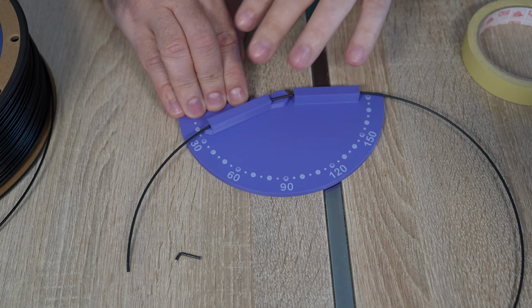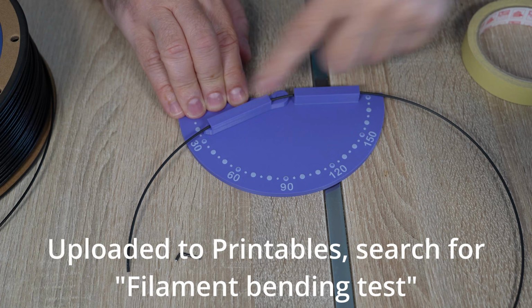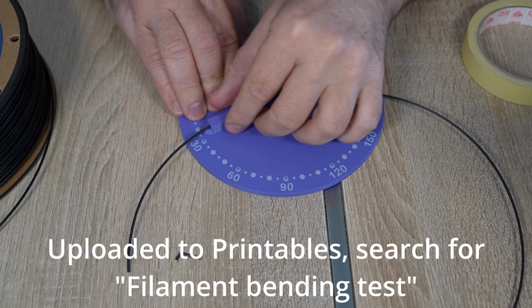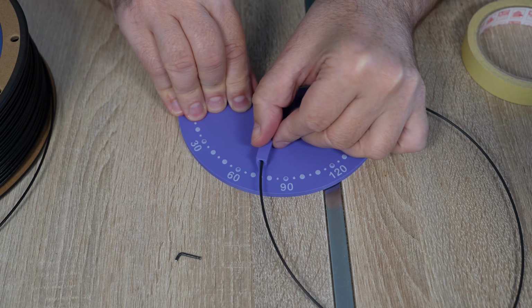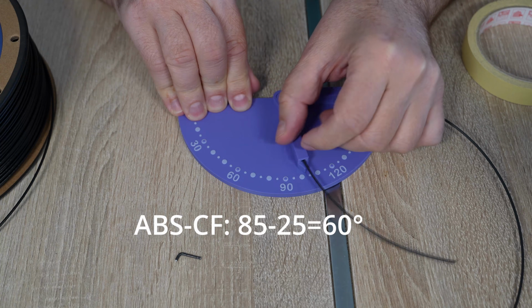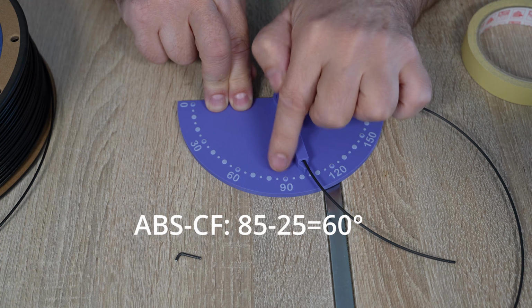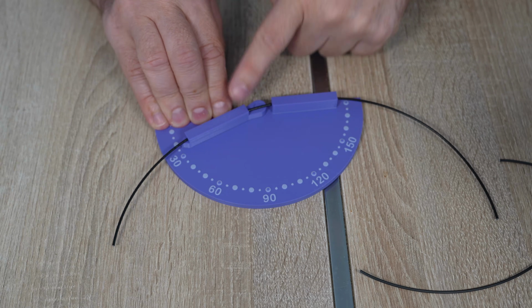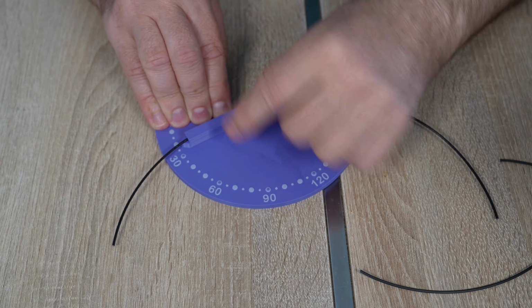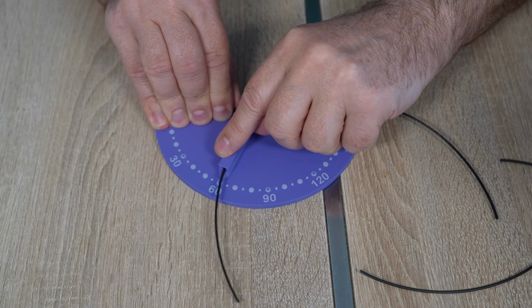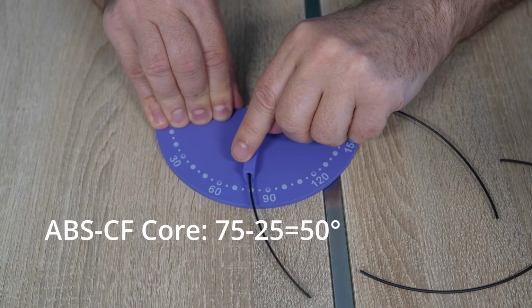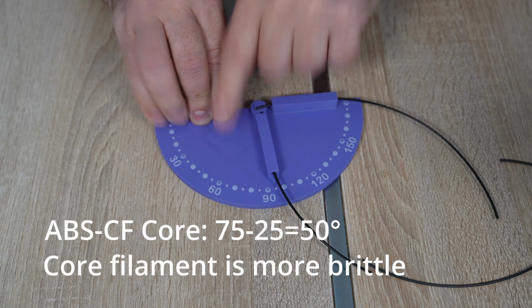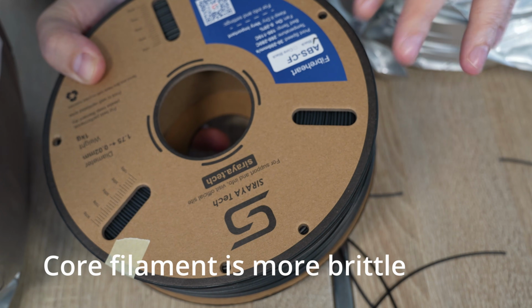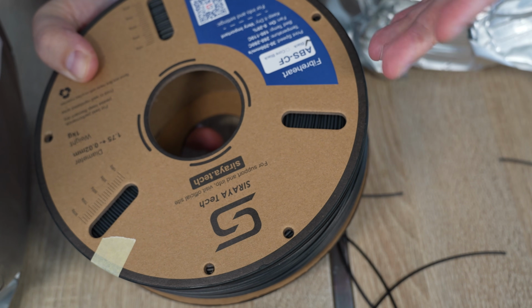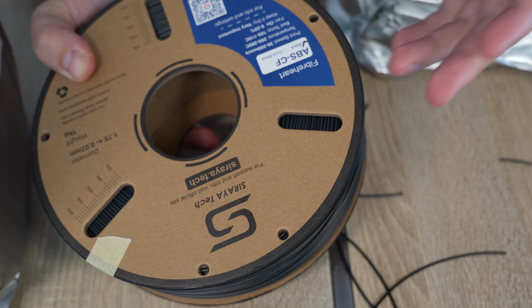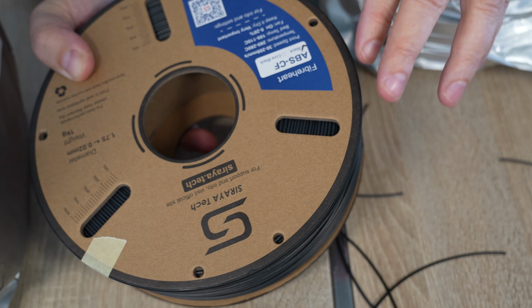Like this. This is the regular carbon fiber version. Start deformation 25 degrees. I will check the footage, but I think it was 85 degrees. This is the core version, start angle 25 degrees. 75 approximately. On the website they mention that it is dried before the packaging and we can use it out of the box. Of course, it depends, if you store it for a longer period, then I would suggest drying this filament.